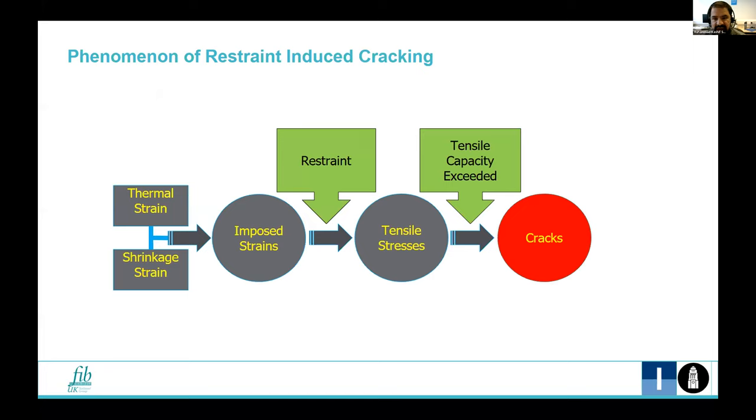When the imposed strains are restrained from occurring due to internally or externally applied restraint, tensile stresses develop in the member, and when these stresses exceed the tensile strength or capacity of concrete, we get cracking which is a major concern in many concrete structures.